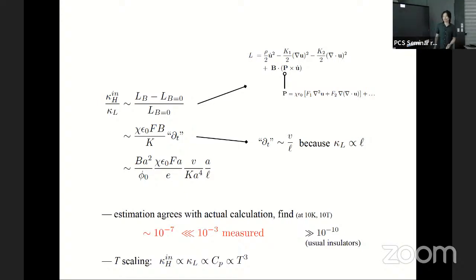So if you do the actual estimation, you'll find that the Hall angle is about 10 to the minus 6 or 10 to the minus 7, which is much smaller than the measured Hall angle, which is 10 to the minus 3. But it's already much larger than the usual insulator, which is 10 to the minus 10. And it's much larger than usual insulator because in usual insulator, this number is order 1, but now in this material it's 20,000. So it's already much larger than in the usual insulator, but still too small compared to the experiment. And also, if you look at the temperature scaling, because kappa L goes as T cubed, and this does not involve the temperature, the kappa H will also go as T cubed. But in a previous slide, I showed that the kappa H in this material goes as T to the 4th. So it also doesn't agree.